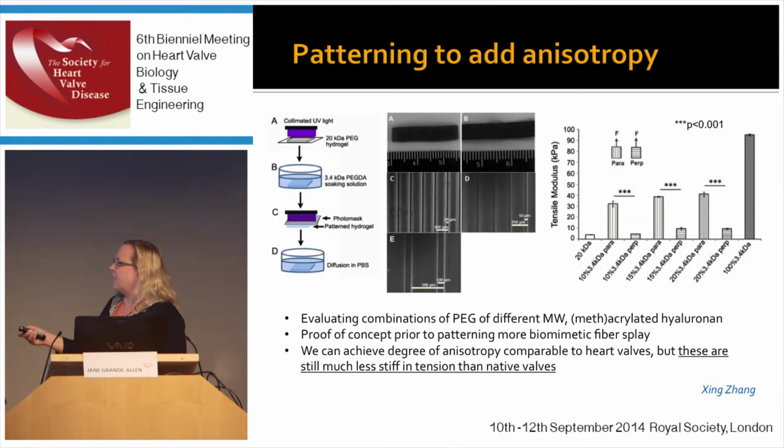But what we're working on here is having reinforcements that are just due to a smaller molecular weight polyethylene glycol fragment being diffused in and then cross-linked via photo cross-linking. And we are able to get increased reinforcement and increased stiffness in the direction parallel to the fibers compared to perpendicular to the fibers in certain volume fractions.